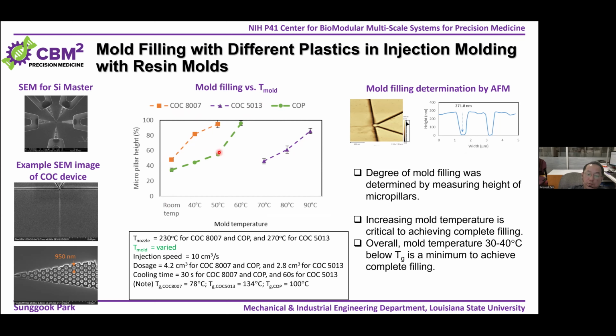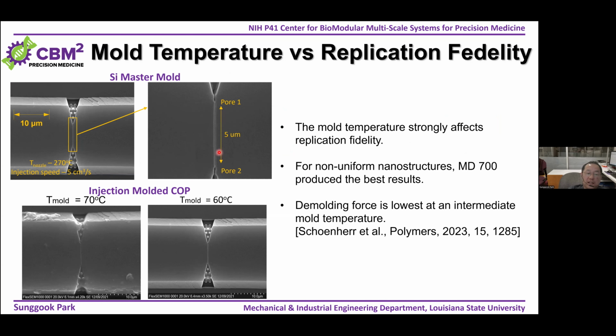However, you also need to consider demolding characteristics. Again, the SEM image shows the master mold structure in silicon, and using this same master mold, we tried injection molding at two different mold temperatures with this MD700 resin mold. What you can find is that as mold temperature increases from 60 degrees C to 70 degrees C, the replication fidelity becomes worse.